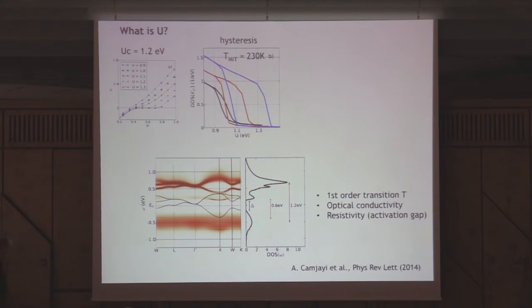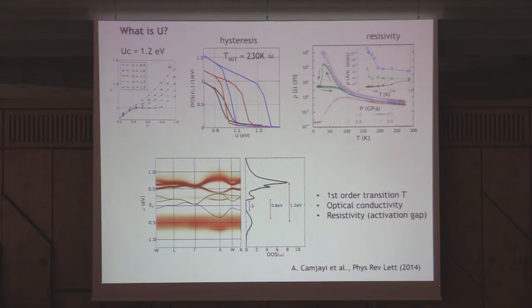And after 6 months, my colleague found this beautiful set of data where you see that at low pressure, there you see the activated behavior. This is the Mott insulator. At very high pressure of 5 gigapascal, you have here the non-monotonic behavior. So this really, if you just forget about that part, only the high temperature part looks very nicely as what Vlad showed us. But the most exciting thing is that in between the insulator and the metal, you have here a huge hysteresis regime, and this hysteresis regime extended to about 100 Kelvin, which is not so bad from our prediction.